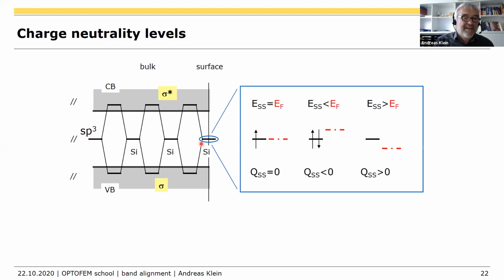And when is this occupied with 1 electron? The orbital can adopt 2 electrons, and it's exactly occupied with 1 electron when the Fermi level is here, because then the occupation probability is 50%. So that means if your Fermi level is exactly where this surface dangling bond is, you have no surface charge. If your Fermi level is higher, you have a negative surface charge because you have more than 1 electron in the orbital. And if your Fermi level is lower, you have a positive surface charge because you have less than 1 electron in the surface orbital. So that means this level is the charge neutrality level. It's the level of this bond.